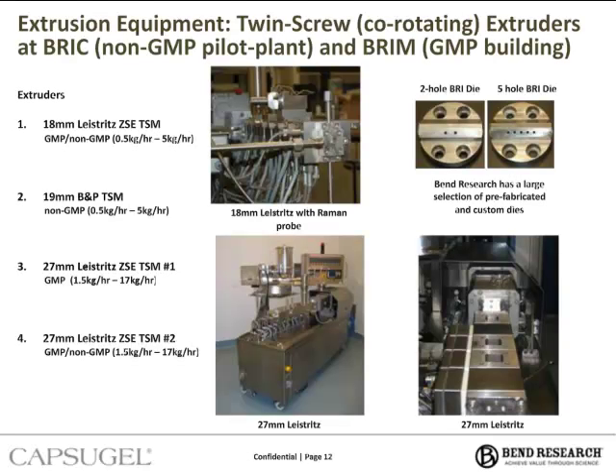Now this slide shows the extrusion equipment available at Bend. So Bend uses twin screw co-rotating extruders, and in our development facility and GMP facility, we have 18 millimeter Leistritz and a 27 millimeter Leistritz. We also, in our development facility, have a 19 millimeter B&P. Now we also have a variety of techniques we use for process analytical technology. We have Raman and NIR, and if you look at the picture with the 18 millimeter Leistritz, you can see there's a Raman probe attached into the die. And the picture on the top right shows a variety of Bend Research's dies. We have a large selection of dies, and a lot of these are prefabricated and custom depending on the application and need.